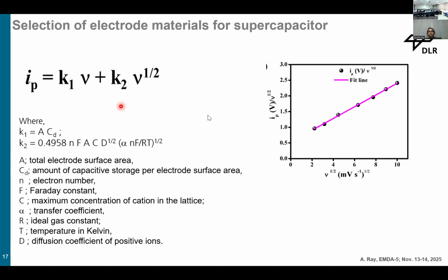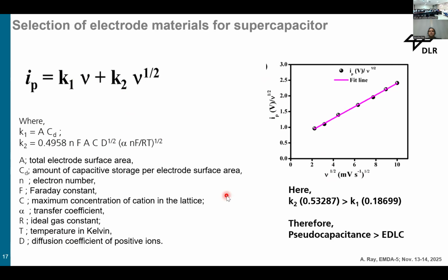And after this, if you plot some data from your CV curve, and you get the slope values from this, K1 and K2 values, this is the general expression you will get in different literature and also in some research papers. And from these K1 and K2 values, you can get all these parameters of your material, and this gives you detailed information about the material. So if K2 is greater than K1, then the pseudocapacitive material is contributing mostly over the double layer capacitive behavior.